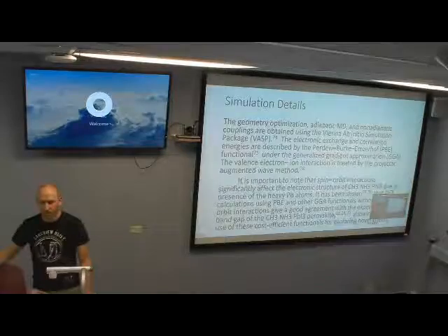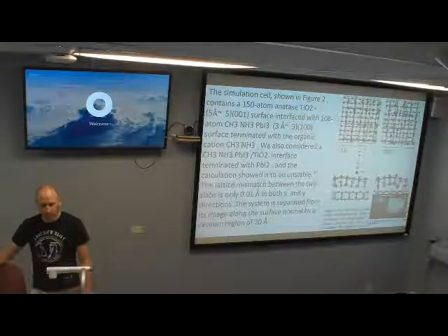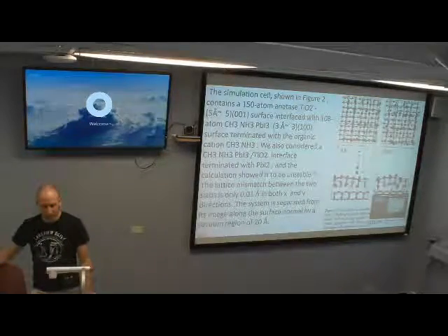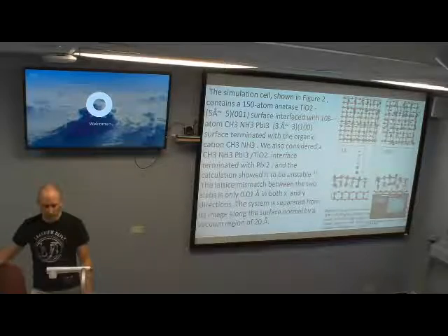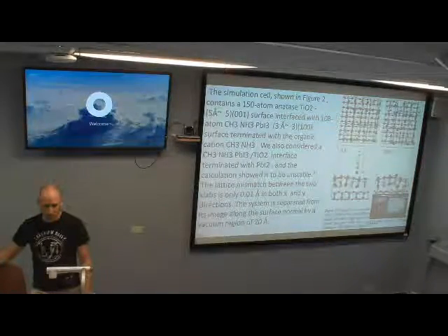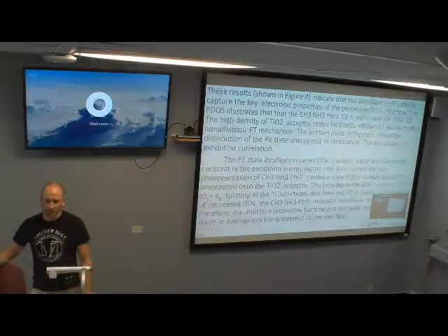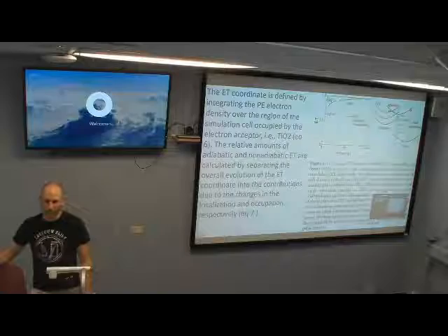And those hybridized states, they claim that this is because of the formation of an iodine-titanium bond. Might be a reason, but the confinement effect probably plays a much bigger role. And they're not showing their ground state orbitals at zero Kelvin, I guess.